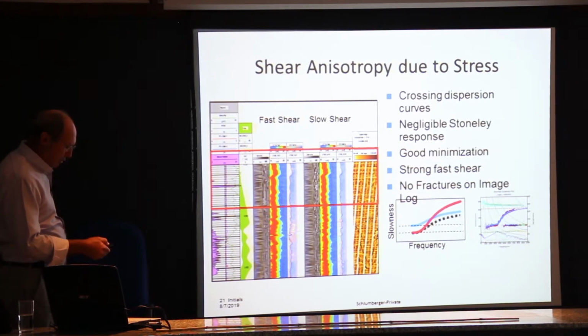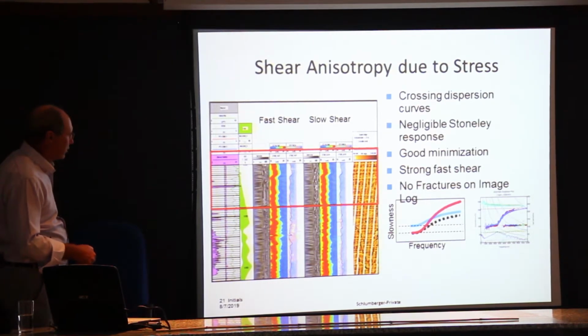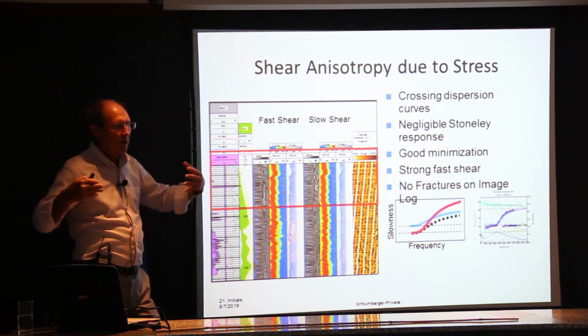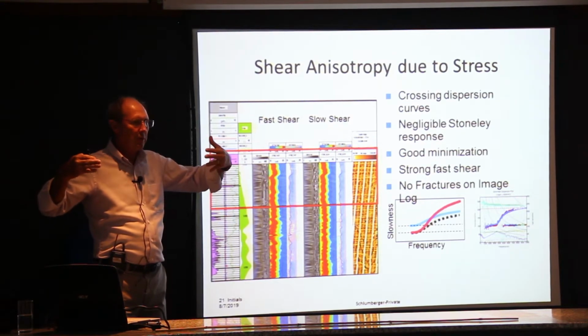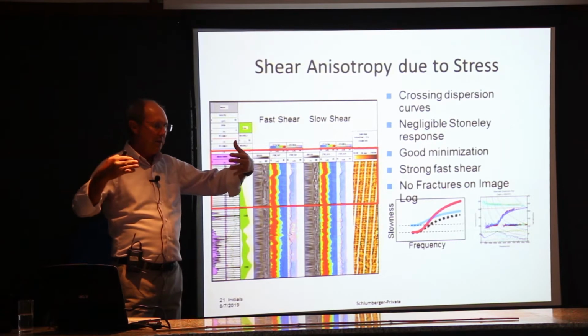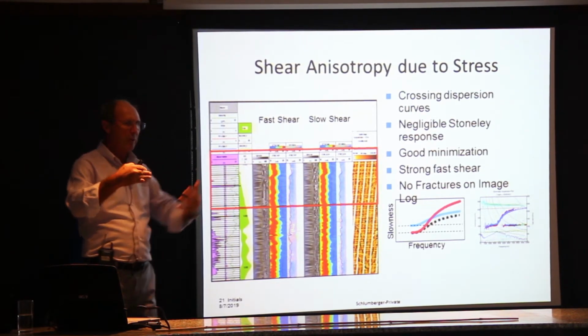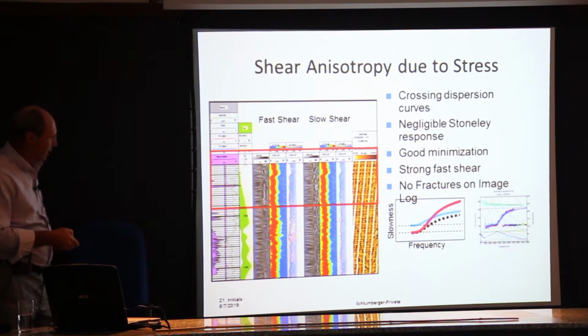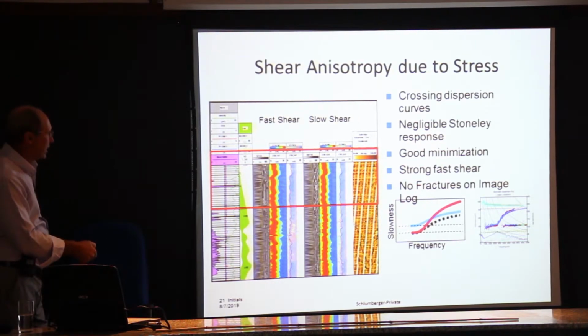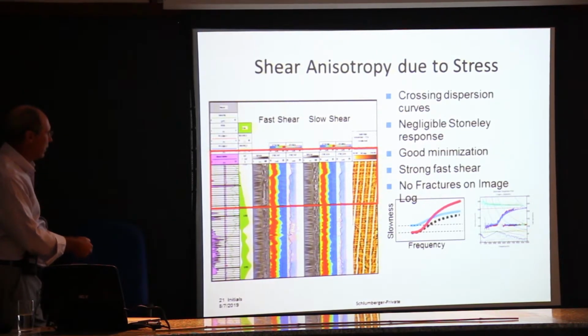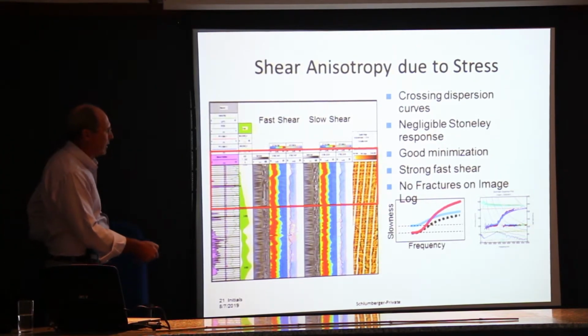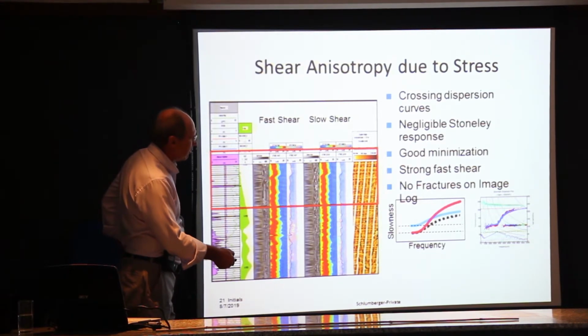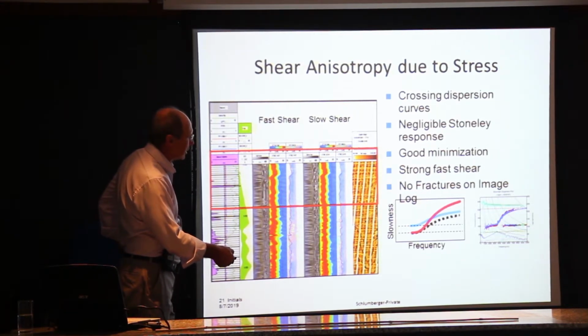Now when you have shear anisotropy due to stress, and you have quite a bit of stress in the pre-salt because of the fault blocks associated with it. Some of the wells, we think the lateral downhole stress is actually higher than the overburden. And up here, we don't really have any clear fractures on the image log, but we have some indications of drilling-induced fractures, and we also have shear anisotropy up here, but we have this crossover effect. You can see a little bit of the crossover effect. It's subtle, but on the log data you can actually see it.